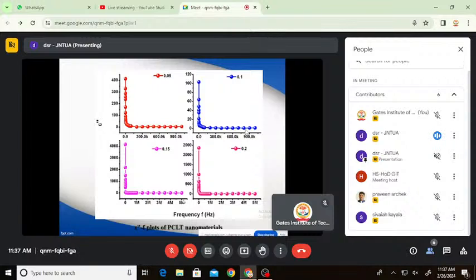When the frequencies move towards higher values, epsilon dash as well as epsilon double dash reduce and remain almost constant. This can be due to the lagging of space charge carriers in following the applied field with increments in frequency. As a whole, the inhomogeneous dielectric structure is accountable for this nature of epsilon dash and epsilon double dash with frequency.